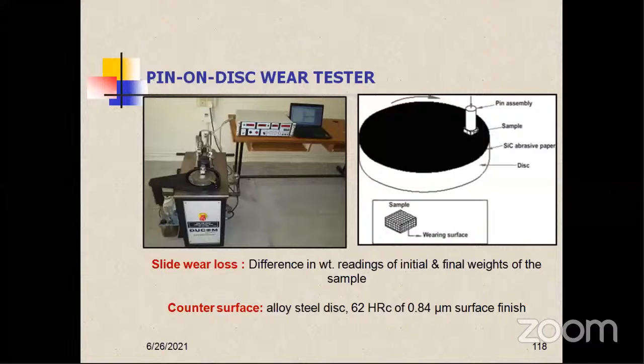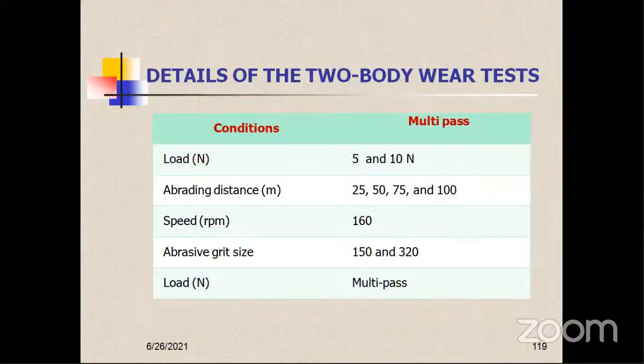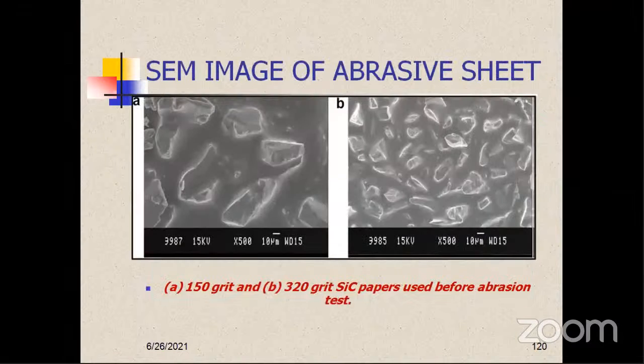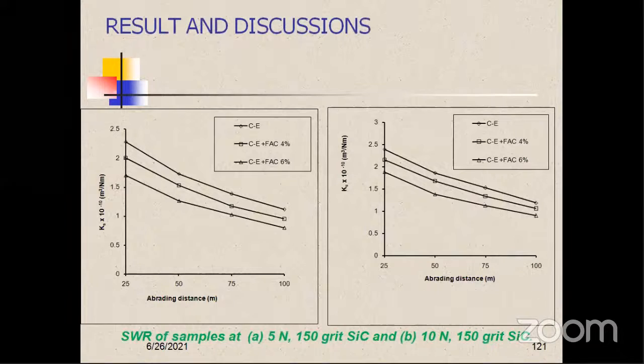And we studied the pin on disc wear test, then also the two-body wear test in multi-pass condition. In the multi-pass condition, abrasive papers with silicon carbide grit were used, 150 grit and 320 grit, for evaluation of specific wear rate as well as coefficient of friction for the fly ash cenosphere carbon epoxy composites. And these are the results for that.